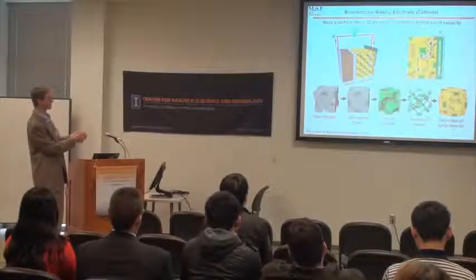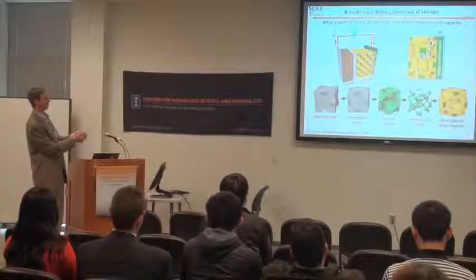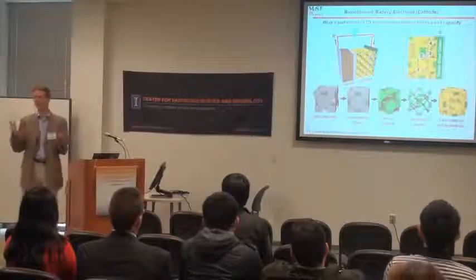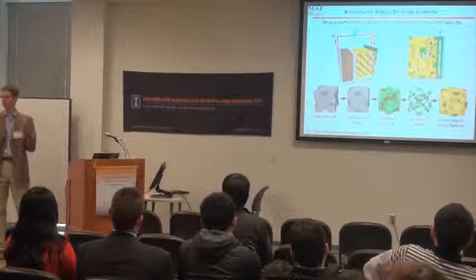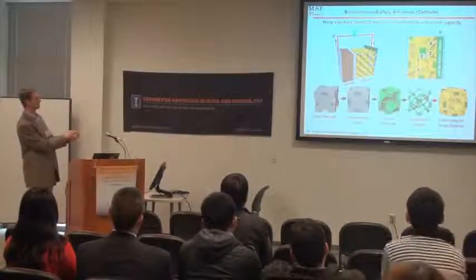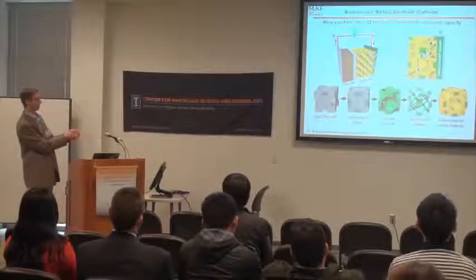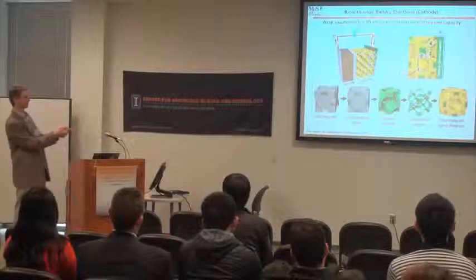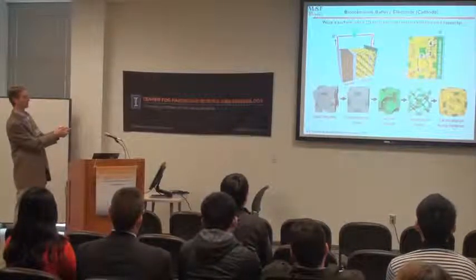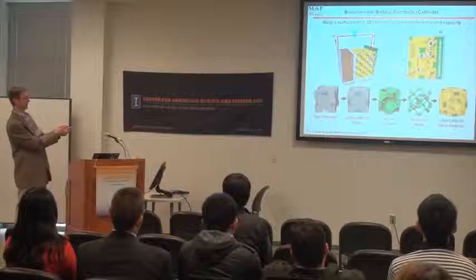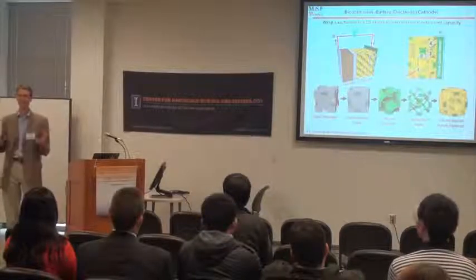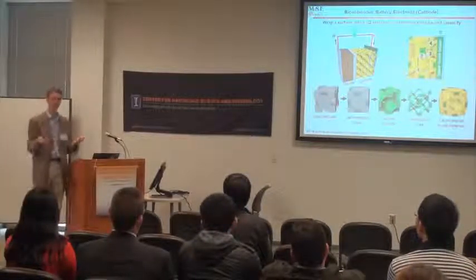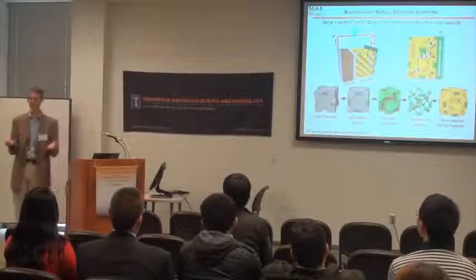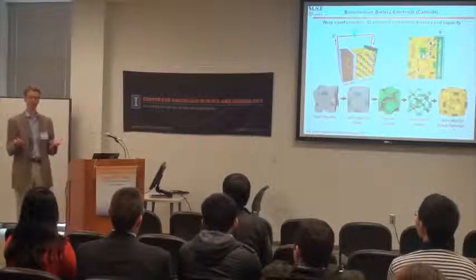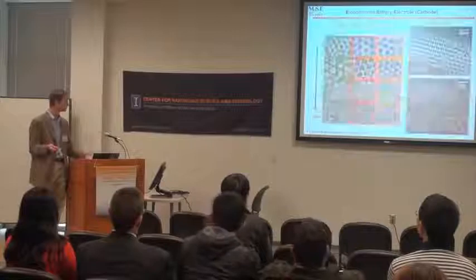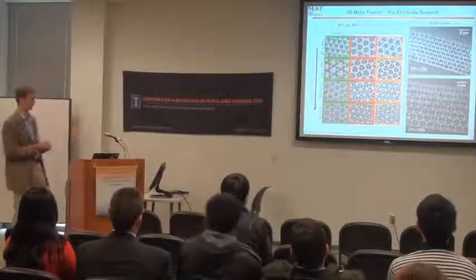And so by electropolishing, it creates this very open metal foam, and then we coat that with active material. And so this is the stuff that stores the energy. And so now we come up with ways to deposit a lot of the storage material and leave a little bit of a pore. And that, in essence, provides a fast pathway for lithium, a fast pathway for electrons, and a lot of active stuff in between. And so there, what you can see is the diffusion lengths are short, but the total volume fraction of material is high. And so the rest of what I'll show you is just the details.